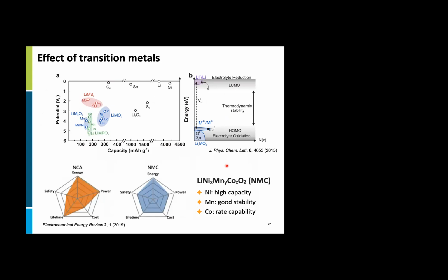To adjust the properties of lithium transition metal oxides, introducing a different kind of transition metal or using a different composition of transition metal may work. For example, lithium nickel manganese cobalt oxide, referred to as NMC, can show much better safety features than NCA. And in general, nickel gives high capacity, manganese is good for stability, and cobalt helps rate capability.